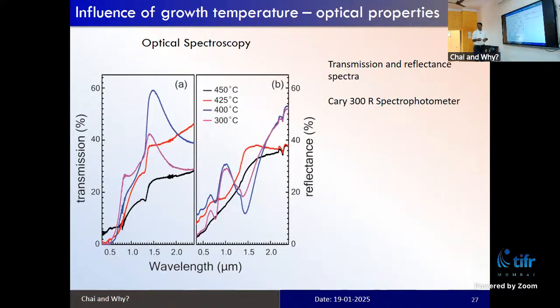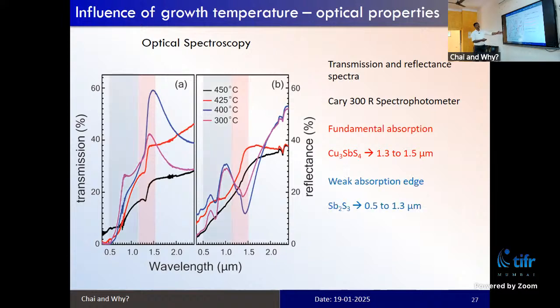So we have also studied the optical properties of this material. Using transmission and reflectance spectra, we can clearly see that there is a band gap. These are the band gap of this material. It has a band offset something around 1.3 to 1.5, which corresponds to copper antimony sulfide, and that's why we can use it for solar cell applications. And there is also sub-band gap absorption, which is because of the impurity present in this material system.